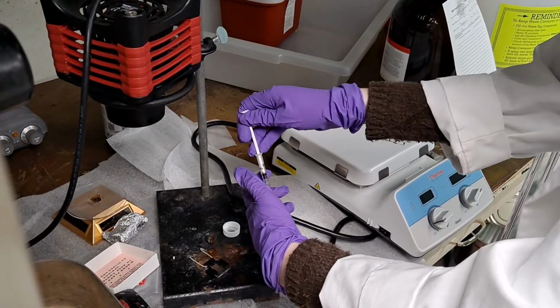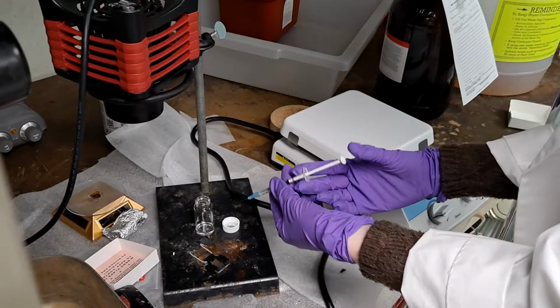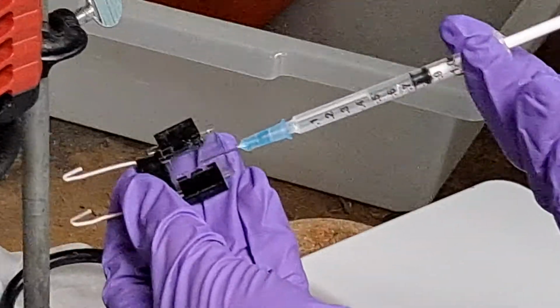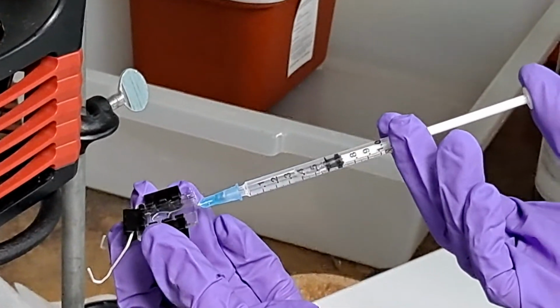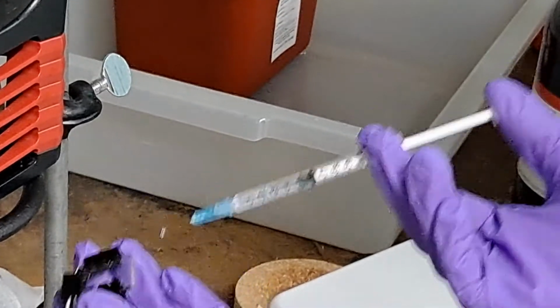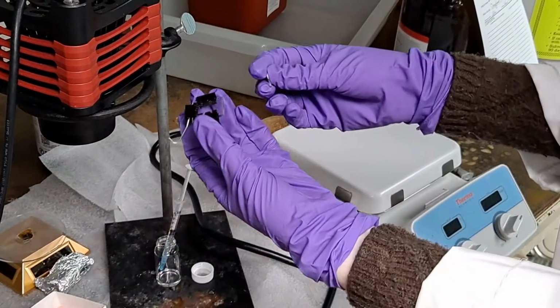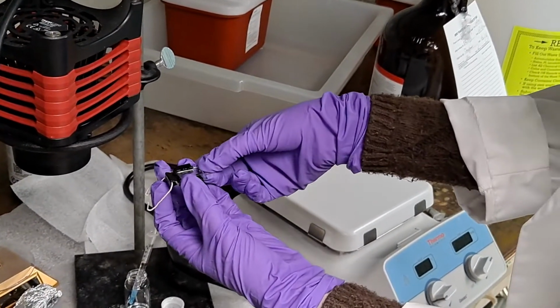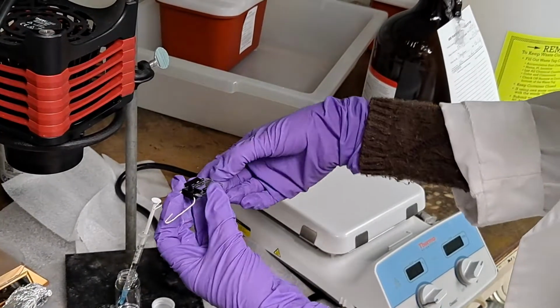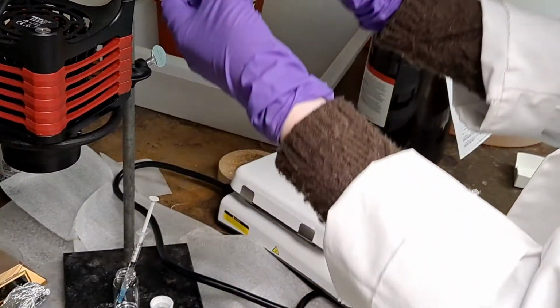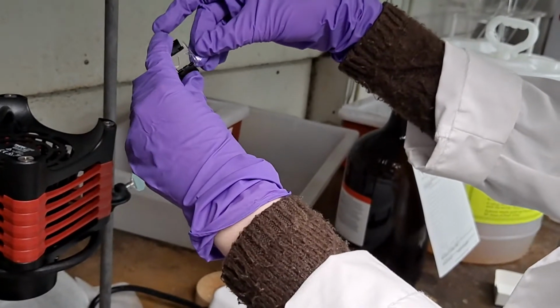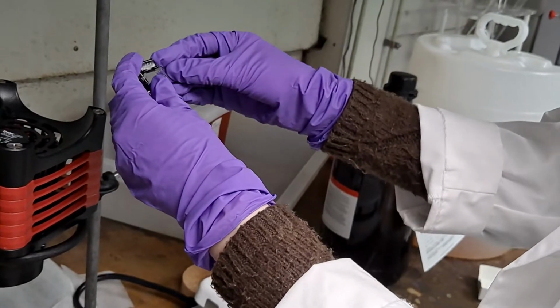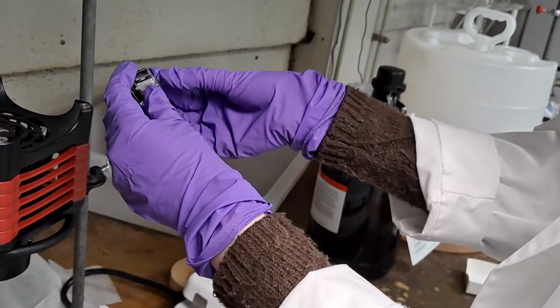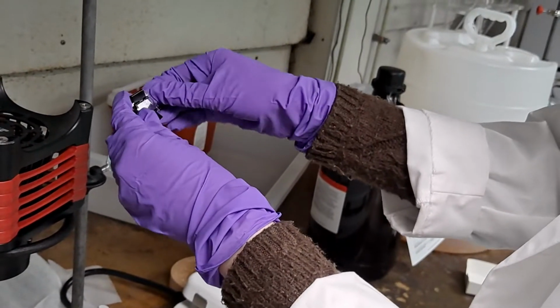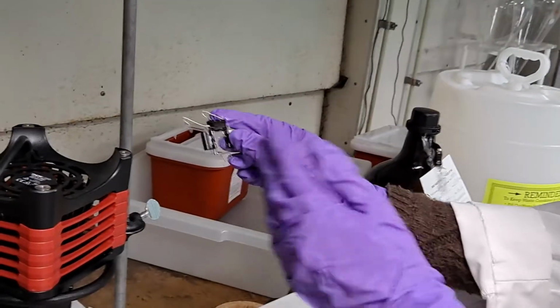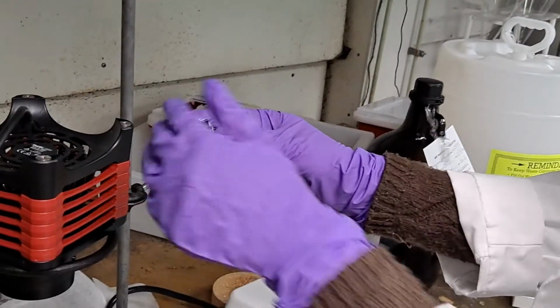Then the sample. Syringe up to 0.3, 0.4 milliliters. Place the syringe, hold it sideways, and you'll insert the needle tip, and you'll slowly inject. And you'll get it to where there's almost nothing left. Put the syringe back. Grab the glass, and you will fit it in that small section. There might be some leaking from the glass, but that is okay. Mainly just trying to get it to fit into the section. There's usually a large air bubble that came from not getting it in quickly enough, but it is fine for our demonstration purposes.